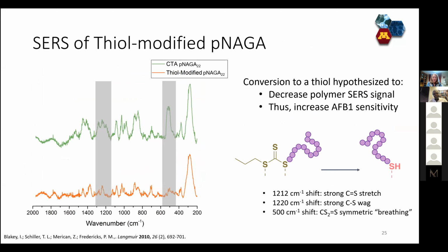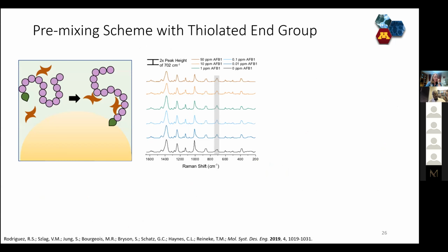So in green is the usual trithiocarbonate, and in orange is once we've turned the polymer into the thiol. And you'll notice that there are a couple places where there's much less spectral congestion. So we were anxious to try the same thing where we pre-mix our thiol terminated NAGA polymer with aflatoxin and then introduce it to our surface to see if we can get an even better limit of detection than the 100 parts per billion we had before. So that's what this data is.